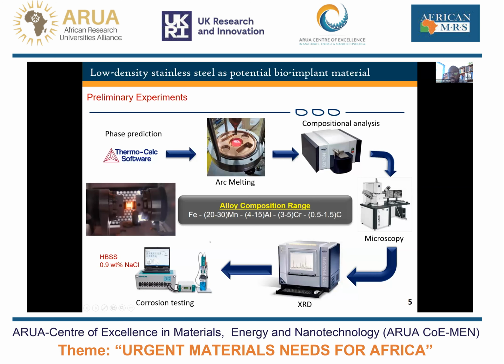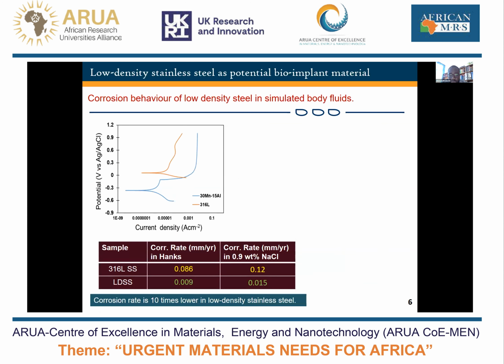So let me just give you a few of the results that we've obtained. In 2021, when we started, what we tried to do was to test the cast alloys in simulated body fluids, carrying out corrosion on them. I'm just showing you one of the many results that we obtained, but this table is what is more important. If you look at the 316L stainless steel that we used as the base material, it's a commercial grade, mind you.